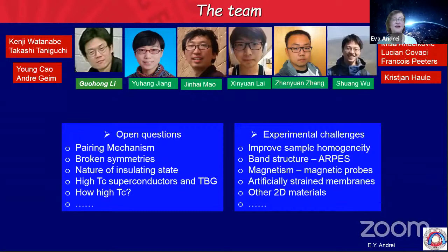And of course, this kind of work raises more questions than it solves. And there are many, many open questions and many challenges, both theoretically and experimentally, that are left. So among the open questions are, what is the pairing mechanism of the superconductivity? What are the broken symmetries? What is the nature of those various insulating states? And we know now that these are topological states. Can it actually help us? Can we get high temperature superconductivity in twisted bilayer graphene? What is the highest TC that we can achieve? So far, the highest TC is about 3.5 degrees Kelvin, which is very small, which doesn't make any dent in superconducting technology.